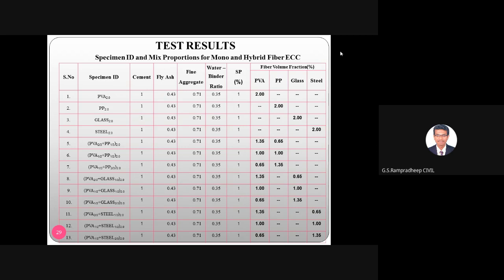Because PVA is giving the high strength, right? So PVA is 2/3 and he is taking PP 1/3 for 2%. Again, PVA 50%, PP 50% for 2%. PVA 33% and PP 66% he is taking for 2%. Simultaneously for other groupings also: PVA plus glass, PVA plus steel. Now you can assume that he is keeping PVA constant. In this grouping, he is not going for PP plus the high modulus fiber.